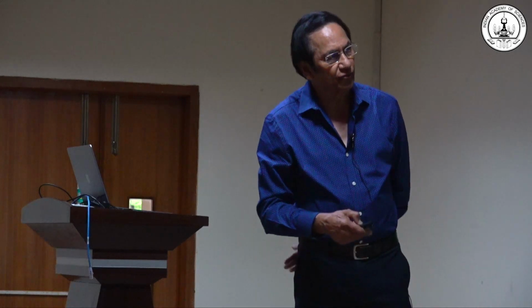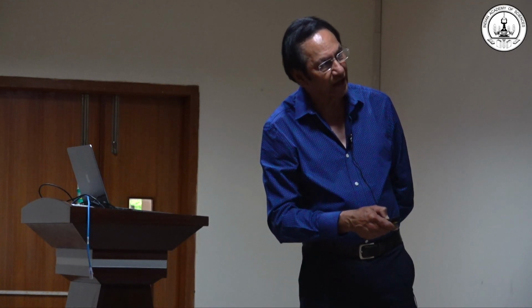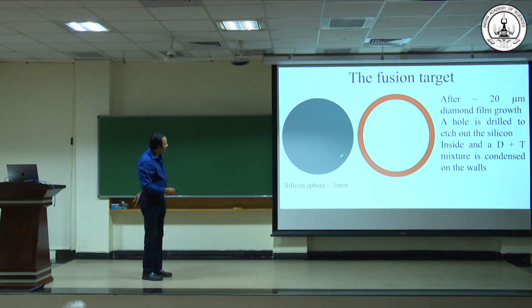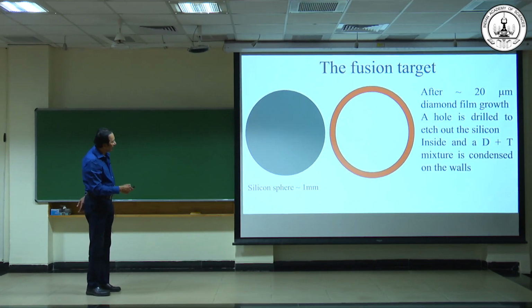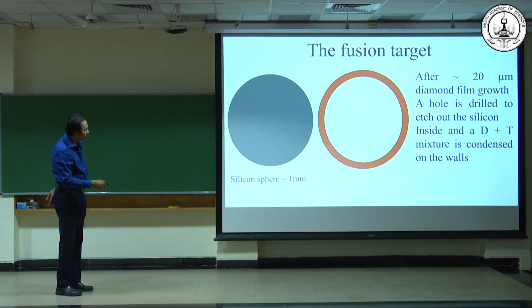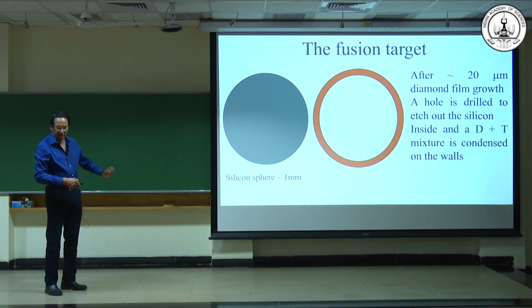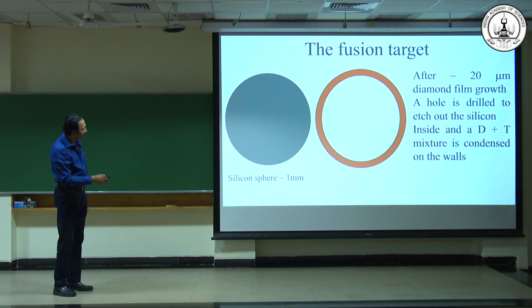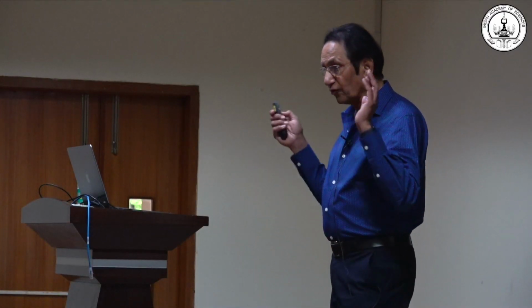How do you produce this? You take a perfect silicon sphere, about 1 millimeter in diameter, and then use a CVD process to grow the diamond on top of it. Then you drill a hole in the top and put in a solvent which dissolves the silicon away, so the silicon completely goes away and you get just the diamond shell. Then through the same hole, you inject deuterium and tritium, at a very low temperature. The deuterium and tritium forms a liquid layer on the inner surface. So that is your fusion fuel.